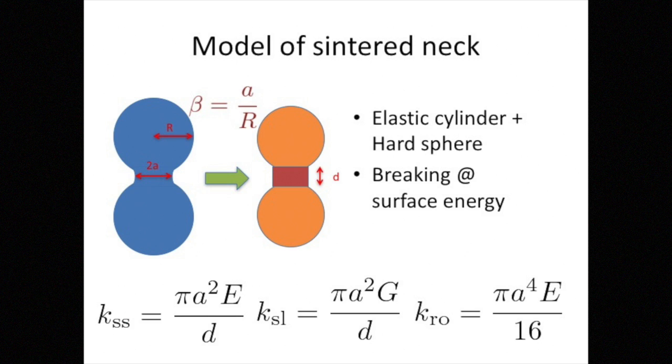I have to give some model of mechanical interaction of a neck. Here, I assume a neck as an elastic cylinder connecting to rigid spheres. Then I can calculate the elastic response with respect to sliding and rolling and stretching motions. And I assume that this neck is broken when I apply enough energy to make new surfaces.